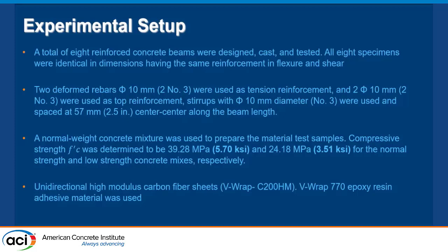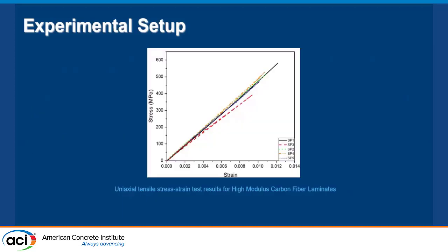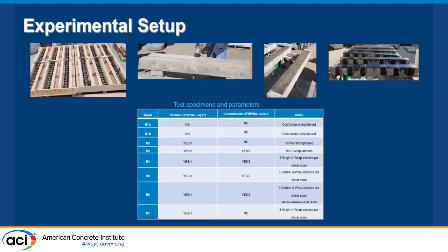Then we used the unidirectional high modulus carbon fiber sheet, the V-Wrap 770, for the tension and the compression reinforcement. That's the experimental stress strain curve for the FRP material that we used. The matrix that we did is 8 beams. The first 2 beams were controls without any FRP reinforcement, just reinforced concrete beams, B1A and B1B. Then B2 has tension reinforcement, just 1 layer at the bottom. B3 has 1 layer at the bottom, and we added the compression reinforcement but without any U-wrap or any kind of anchors, just to see the effect of the compression without anchoring.